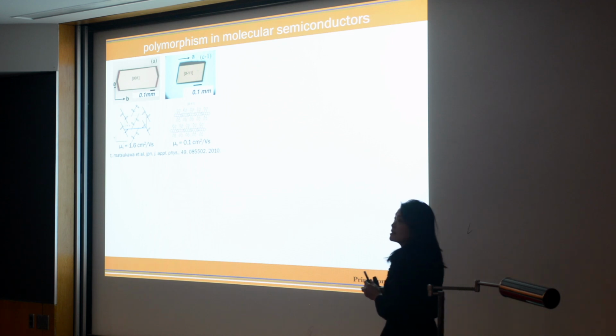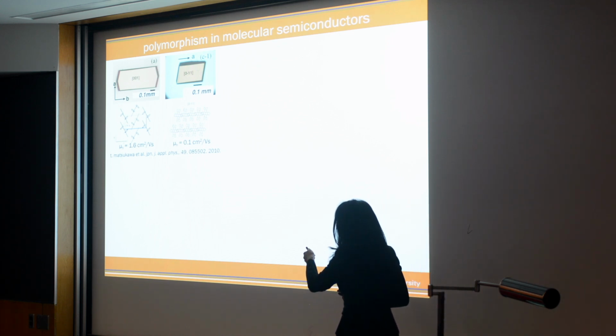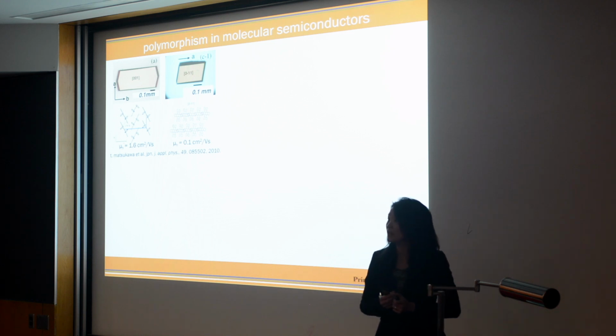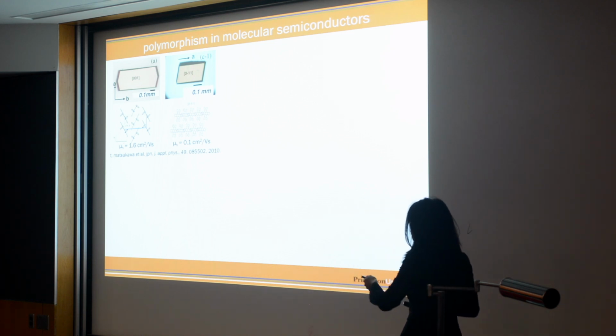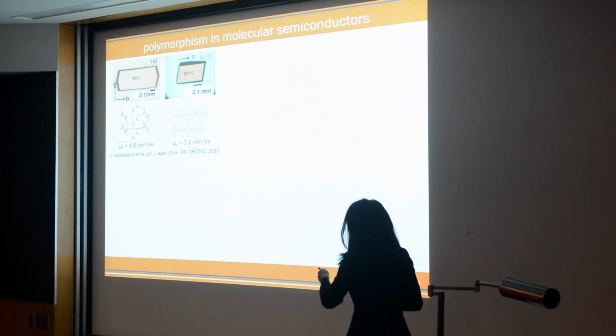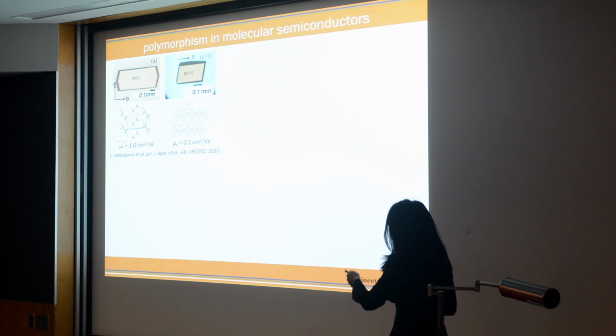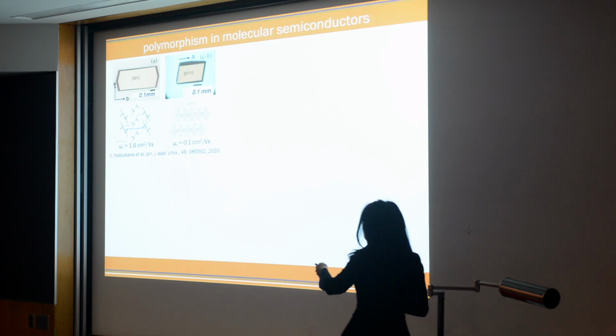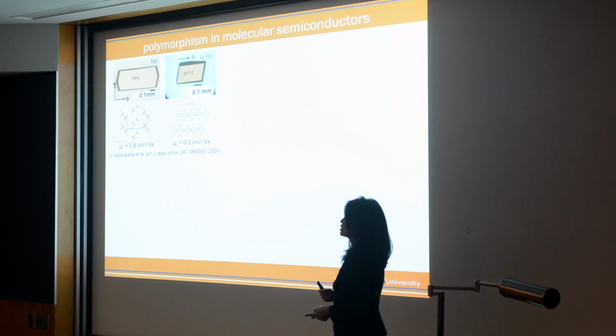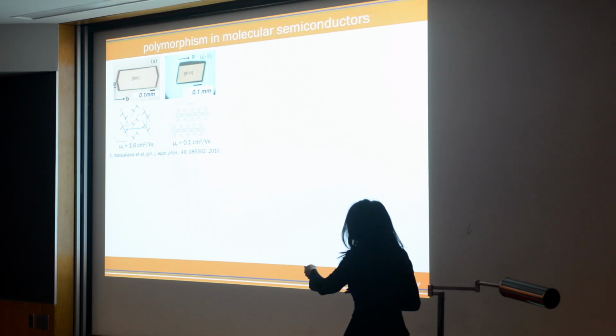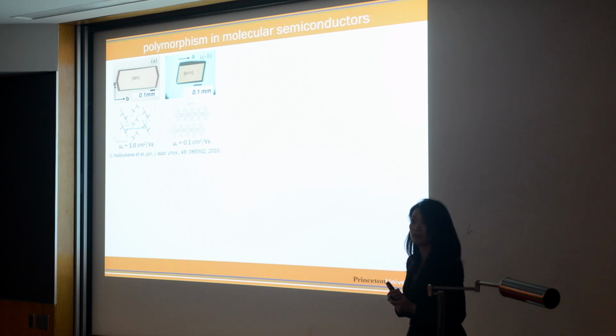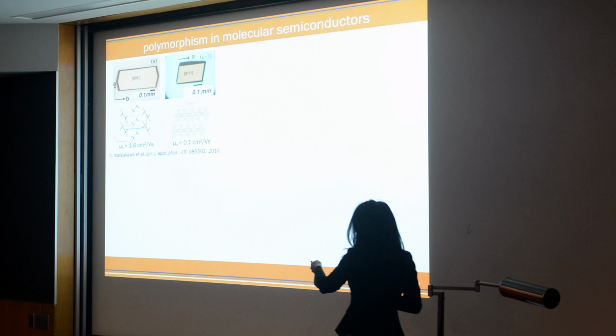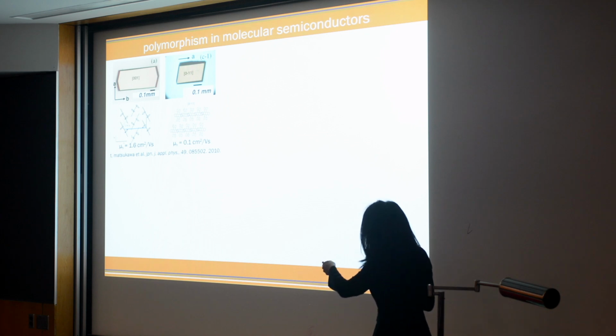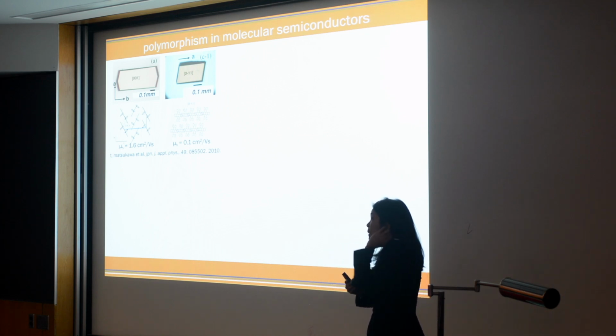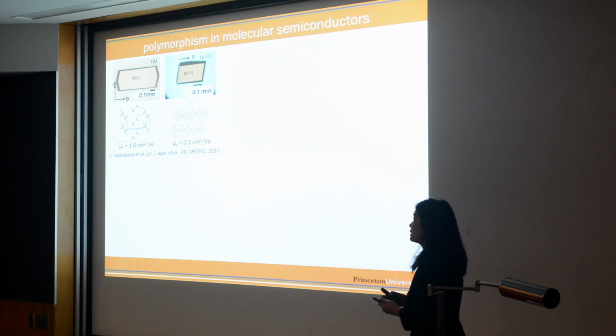So this is rubrene. It's a quintessential organic semiconductor. You can grow macroscopic single crystals of this rubrene. And you can grow rubrene in different forms. You can grow it in its orthorhombic form or its triclinic form. And these are the crystal structures that are shown here. And then depending on which crystal structure you access, you can see that the mobility, which measures how efficiently charges are transported in these materials, could be quite different. In its orthorhombic form, it's 1.6 centimeters squared per volt second. In its triclinic form, it's only 0.1 centimeters squared per volt second. Big differences, again, because here you can see, even in these crystal structures, that the extent of pi orbital overlap and electronic coupling is very different.